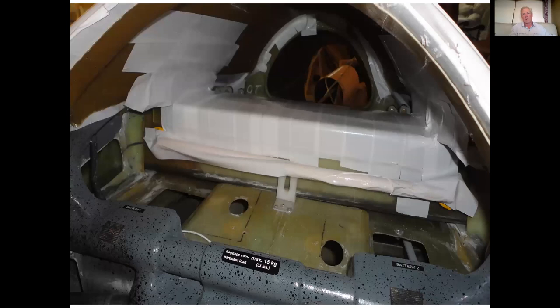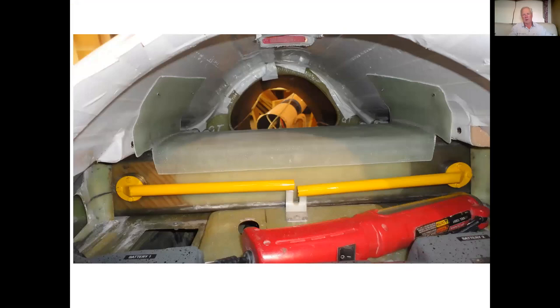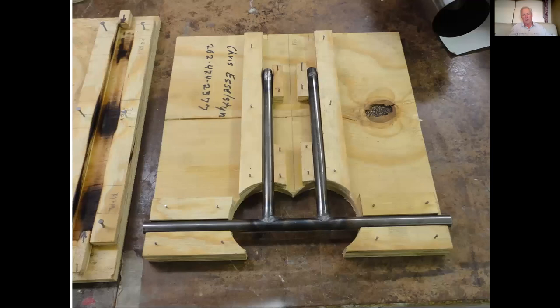On the spar, I put a quarter inch of foam and then duct tape over the foam and up onto the fuselage sides and inside the turtle deck, and made a layup. And that's a saddle that you're looking at here. What I'm trying to do is keep the relationship all sound between the spars, the saddle, and the inside of the turtle deck. Next thing is making up some fairly simple